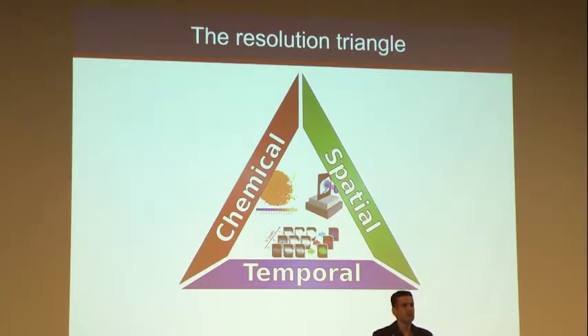And so for us, we need to be able to follow a reaction as it happens, and that has an implication of time resolution. And we need to be able to actually follow the reaction. And so we need to follow chemistry. You're going to see that there are moments where you sacrifice and you miss important information if you don't take this into account. And so we think of it as kind of like the fire triangle, that you need 3 components to get a fire. Well, you need 3 elements for a good chemical imaging to provide the insight that you're looking for, at least for a battery reaction. And so I'm going to discuss development that we've been able to contribute to in all 3 sides of this triangle.